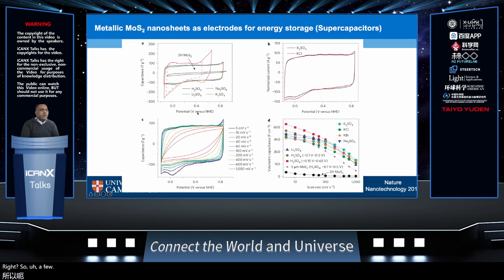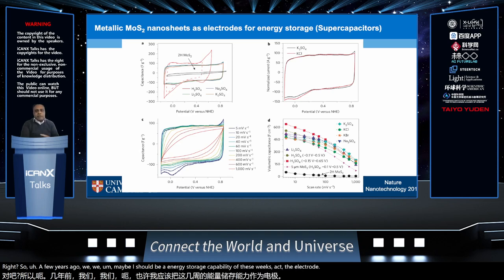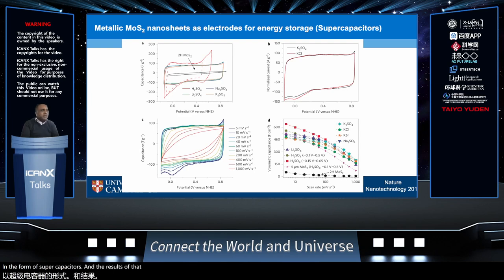A few years ago, we measured the energy storage capability of these restacked electrodes in the form of supercapacitors, and the results of that study are shown here. The cyclic voltammetry data, where we plotted the gravimetric capacitance as a function of potential, are shown here for different electrolytes. If you just make electrodes from the semiconducting MoS2, it's too insulating to give any appreciable capacitance values. However, with the metallic phase 1T MoS2, we get these nice CV curves and a substantial amount of charge storage.